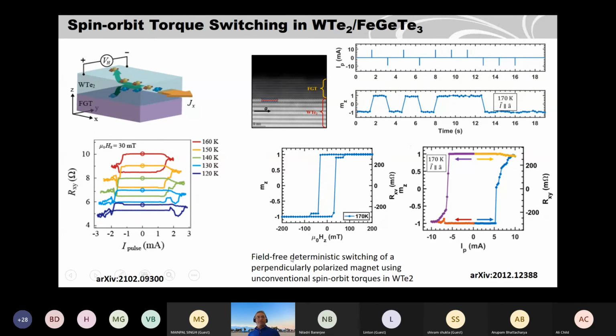And also recently some arXiv papers in this direction show that tungsten telluride can be used to switch a 2D magnet. And 2D magnets are mostly perpendicular, like iron germanium telluride. This is tungsten telluride, so they make this van der Waals heterostructure. By passing a current in tungsten telluride, you create the spin polarization, and you can then switch the magnet. This switching can also be done with a pulse current, and this is the temperature dependence, because this magnet, iron germanium telluride, has a low Curie temperature. So this is limited to low temperature, but it should be possible if we find 2D magnets with higher Curie temperature.